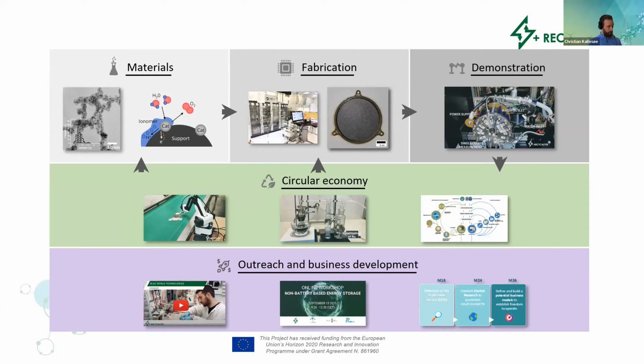First of all, can we completely use new alloys without critical raw materials? And if not, how can we alloy the critical raw materials with some other elements to boost the activity? And then we look at how to utilize support structures. So the small illustration here is to have a very small catalyst particle on a little bit larger support particles, so we can lower the volume of the catalyst particles, but increase the surface area and hence boost the activity. And with a combination of alloying critical raw materials with nickel together with using a support structure called antimony doped tin oxide, we have actually shown catalyst activities which are 100 times better than commercial alternatives, which will allow us to reduce the amounts of catalyst used in the demonstrator.